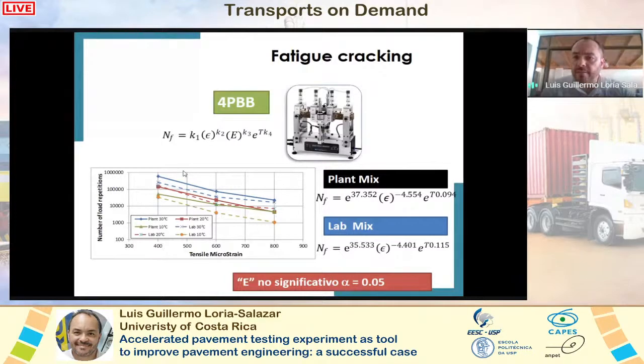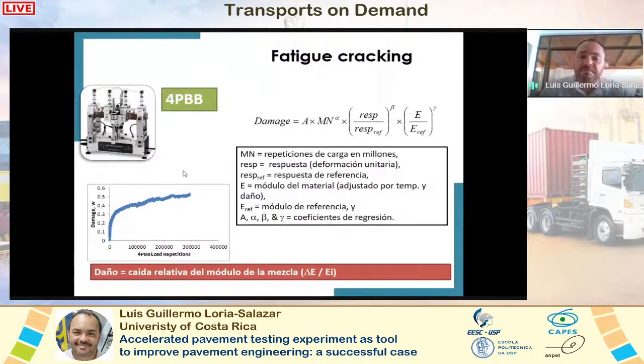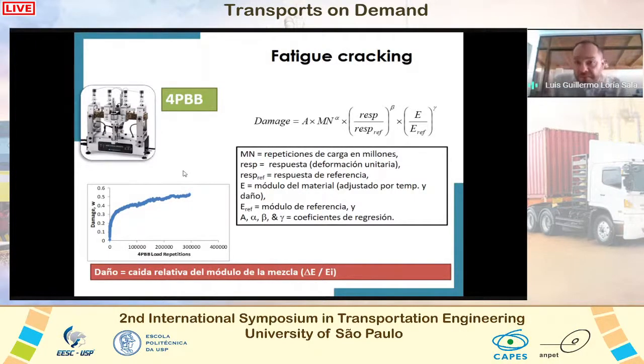We also perform fatigue cracking. In this case, we use the 4-point bending beam, and we use plant mix and also laboratory mix in order to calibrate the fatigue at the lab stage and the HVS stage. For the field stage, since we didn't have a real measure of cracks, and it was not easy to measure the cracks, we developed the shift factor or the calibration model using a damage concept that you can see over there. So basically, we determine the damage at each cycle applied at the lab with the 4-point bending beam and the damage at each cycle in the field, taking the damage as the reduction in the dynamic modulus of the HMA layer. So that was the concept.